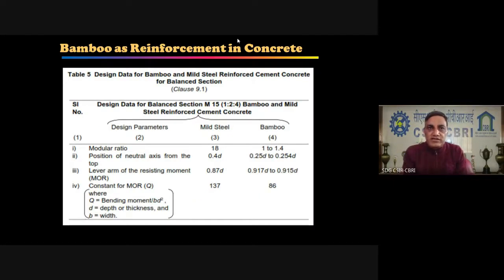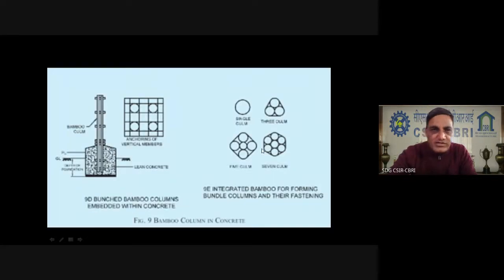When you are dealing with the design, the data you further require is the modular ratio, the position of the neutral axis from the top, the lever arm for resisting the moment, and the constants for moment of resistance, so Q, that is the bending moment, then depth, thickness, and width. These ranges are given here for the bamboo. The modular ratio can be taken in the range of 1 to 1.4. The position of the neutral axis from the top could be 1/4 of D, that is 0.25 D, where D is the effective depth of the structural element. Then the lever arm of the resisting moment could be 0.917 to 0.915 D, and the constant for moment of resistance Q can be considered as 86. These are very important figures which can be considered while designing bamboo reinforced concrete elements.